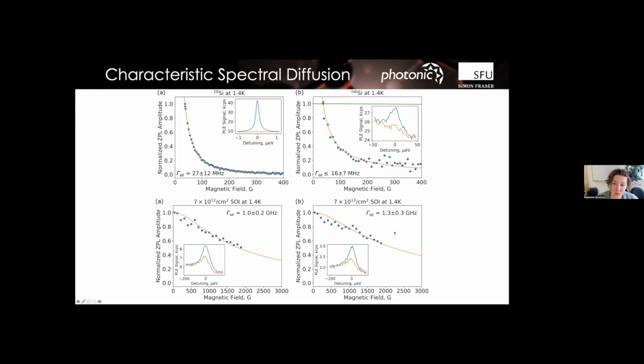And when we did that same measurement in our SOI that we basically made near amorphous, we were getting something like a gigahertz, which, okay, improvements need to be made, right? But that's a starting point, and we've been iterating since. So that's the kind of starting point where you really want it to be about an order of magnitude less than that. But I will say that this is already a lot better than what we've seen from many other color centers in devices, right? Devices just seem to have this interface quality, and different defects coupled to the different noise sources of different interfaces differently, as you would expect. And it seems like this is actually a really good starting point for basically having done zero optimization. We're already off to a really good point.